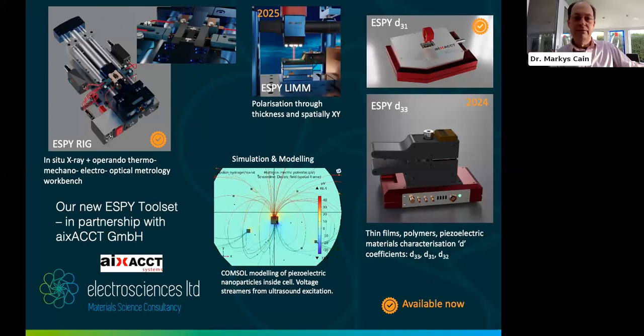Yeah. So we had a problem where we were trying to measure d33 on a composite material, so a ceramic powder suspended in a polymer material, and this case was KNN. And what we observed is that it was extremely sensitive to humidity, and we know KNN is sensitive to humidity, but what we observed is that over seconds, when the material absorbed humidity, the d33 increased significantly, a factor of 2 almost. And I don't know that we really understood the mechanisms, but maybe you can speculate on that.